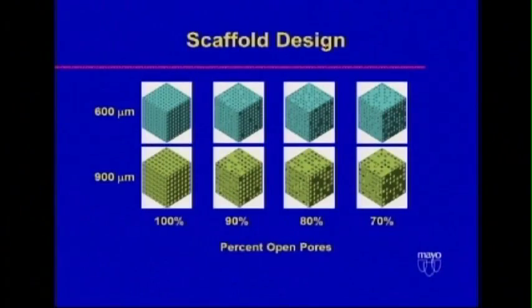This is the work of Kiwan Lee. Kiwan was one of my graduate students a couple of years ago, and he did a PhD thesis that incorporated SFF. We use AutoCAD, Pro Engineer is what we use. We make an STL file out of it, a stereolithography .stl file, and we feed it to the machine, and the machine makes a piece. So Kiwan just showed that if we made a scaffold, if you will, that had rectangular geometry, external and internal, he could close off pores, he could change the size of pores, he could change the width of the struts.